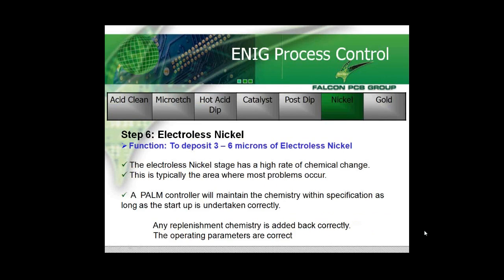And coming to the most troublesome issue of the whole of the ENIG process, electroless nickel. It causes a lot of problems. It runs hot, approximately 90 degrees centigrade. There are a lot of problems in particular with the amount of metal turnovers, again described well by Nigel. And what we tend to find is as you use the bath longer, of course, it can build up more contaminants.